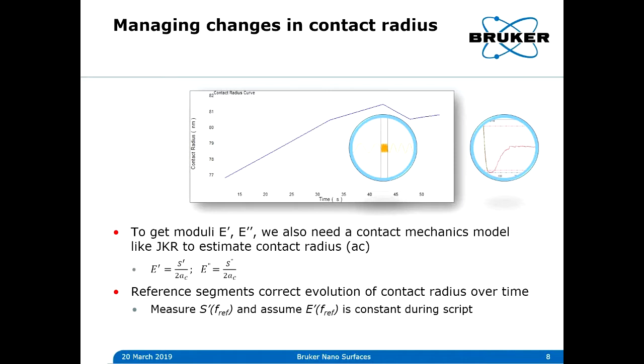I mean, this question asker is probably somebody that's pretty familiar with DMA, because it is also an issue for bulk DMA machines. The issue is that essentially there can be frictional heating within the material when you start vibrating it, and that could cause a temperature shift in the measurement. With AFM, we have that. We also have a laser on our cantilever. The temperature is not completely uniform around the cantilever, so there is some uncertainty in the temperature of the sample where it's being interrogated. But so far, with the measurements that we've done, it looks like we're within a couple of degrees of what we think we are.